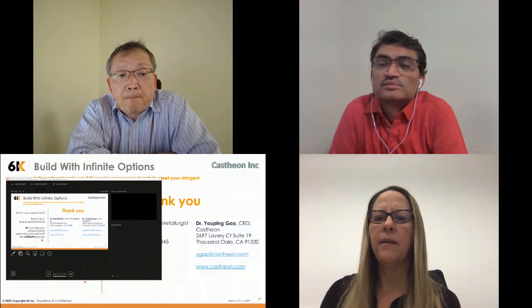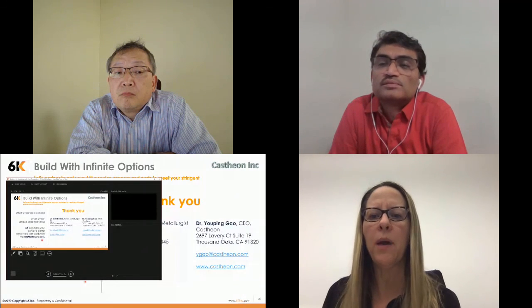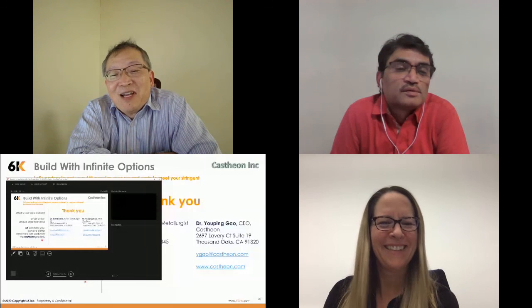Okay, great. Simon had asked, mechanical alloying can assist super solid solution, but once the alloy melts via laser melting, how do you overcome intermetallics formation? So it depends on the alloy chemistries, and sometimes you can control it, and sometimes you can't. In this case, there's no preference only because they're mixing pretty well. So we do see some segregations, but they're still in the alloying form. So we haven't seen strong formation of the intermetallic yet, but I'm sure once you start to play with the chemistries and scale in one of the directions, you're going to hit some intermetallics forming.